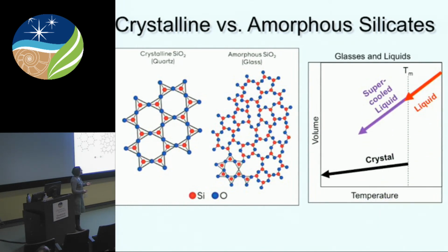To form a glass, what you do is you cool the liquid past the melting temperature without crystallizing. And so the atomic rearrangement slows down. And eventually, you're going to reach some temperature. This is what's known as the glass transition, where the atoms aren't able to rearrange on the time scales of observation. And that's when you form a glass. So the important thing here is that glasses are effectively frozen snapshots of liquids. And there's some information that we can extrapolate to liquids by understanding the properties of glasses.